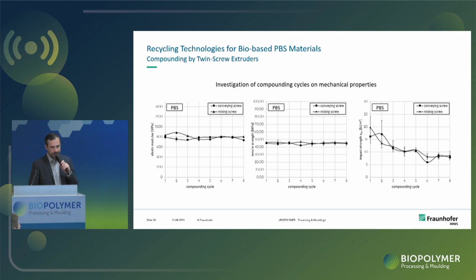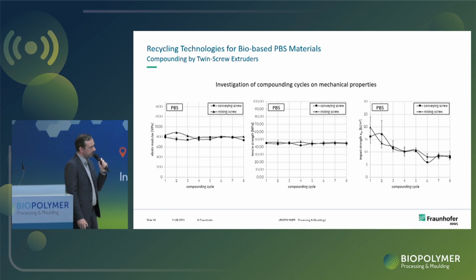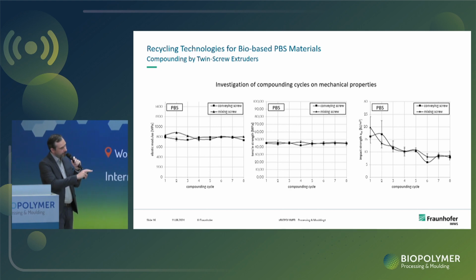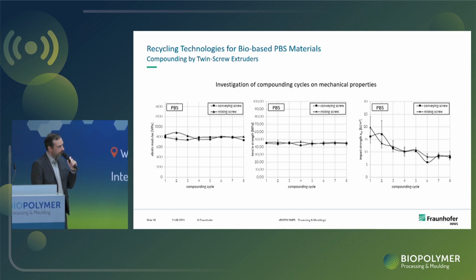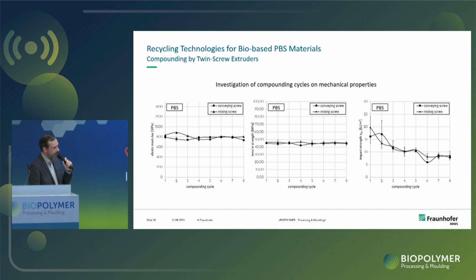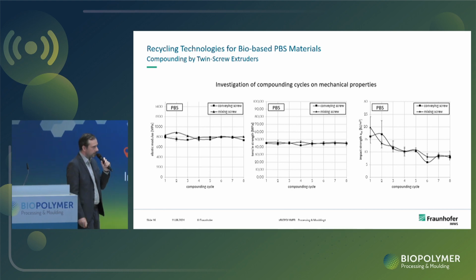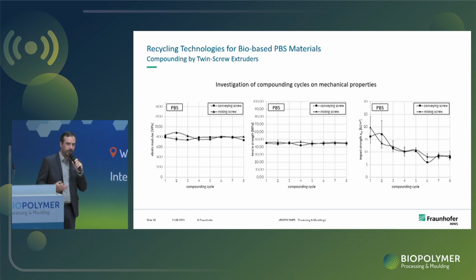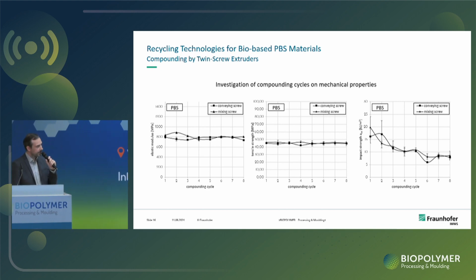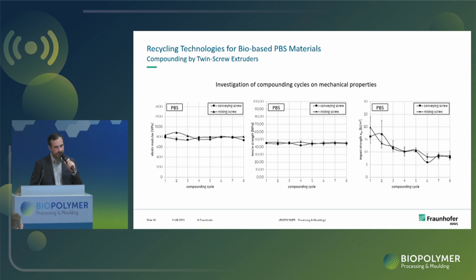Interestingly, we could not find any decrease in the mechanics, so stiffness and strength is more or less stable, but you see this decrease in molecular weight in the impact strength on the right diagram. A decrease in impact strength is also a clear sign that a reduction in molecular weight happens during this reprocessing, and this of course is information that you always need fresh material. To make new products out of completely recycled material will be very hard and very challenging.